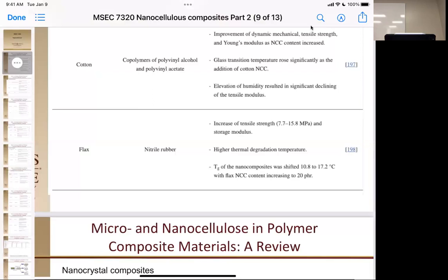So why would it have a higher thermal degradation? I think it's because you have like 18% nanocrystals there, and the nanocrystals decompose later than nitrile rubber, so your onset gets shifted out because your nanocrystals haven't started to decompose. But they didn't give a reason for why it was higher. And again, it was only like 5 or 10 degrees, so it could easily be lost in this curve. But this is reproducible and significant.